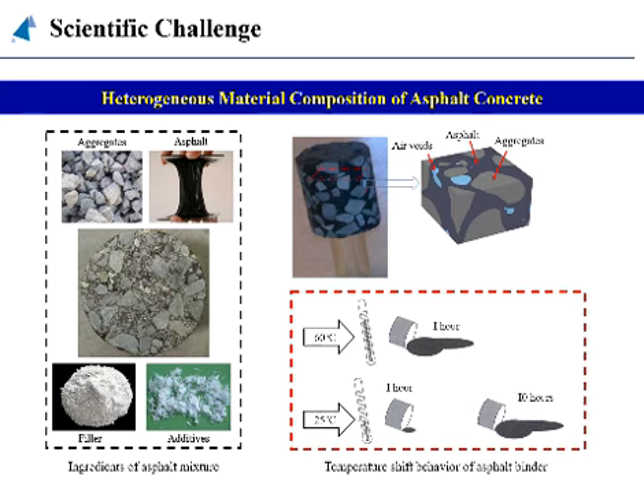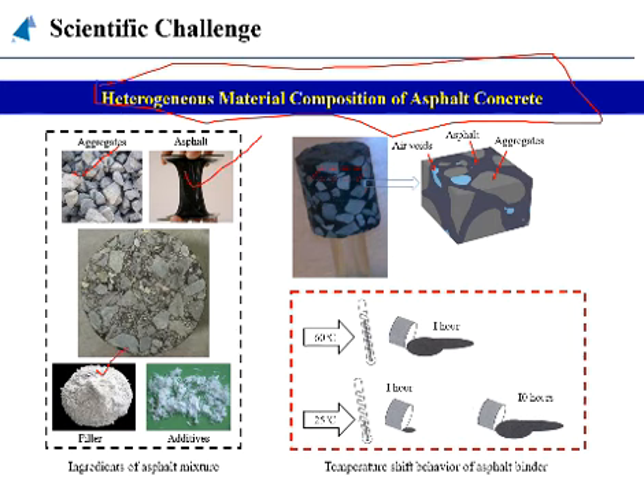Our asphalt concrete has a very heterogeneous composition, meaning that it is composed of different materials. On one side we have aggregates, on the other we have asphalt or bitumen, and we have some filler, and we have some fibers, which are the additives. Among all these things, this one is very sensitive to environmental variation. Like we see here, it is 60 degrees centigrade for 1 hour, and this is its state. At 25 degrees for 1 hour it is like this, and for 10 hours it is like this. So this basically shows the temperature shift behavior of the asphalt binder. It shows how, with the increase of temperature, it changes its status.